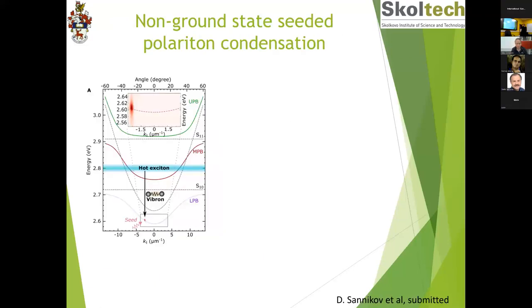And we did this work by now using the concept of non-ground state polariton amplification. So everything I have been talking about so far concerned amplification of the ground polariton state. But imagine now that your control beam, the seed beam, does not come at the ground state, but it comes at a small angle, where just angularly you can separate very easily the emission of any light that you get out from this state with respect to what you would get from a polariton condensate. So we now tune the vibron, the energy transition that relaxes you from the hot exciton to the seed, to be resonant with this non-ground state. And we are looking to see if, when we have the seed present, we can get amplification there.